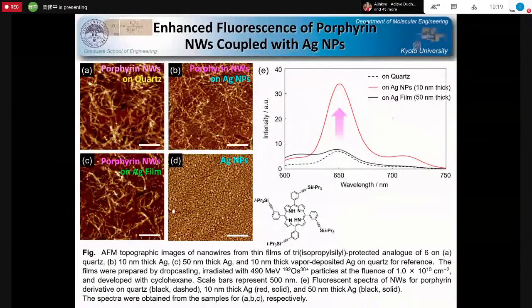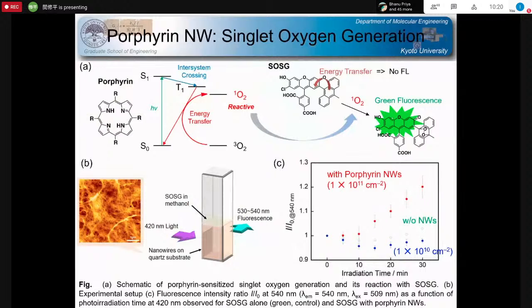This is a case of more efficient light harvesting, in which the porphyrin nanowire was coupled with metal nanoparticles. And as you know, metal nanoparticles have very strong plasmon resonances. So the plasmon resonance energy was directly converted into the porphyrin nanowires and successively converted into chemical energy, as demonstrated in the next viewgraph. In this case, after the excitation of the plasmonic metal particles and conversion into the porphyrin nanowires, the excited energy was again converted into chemical energy.